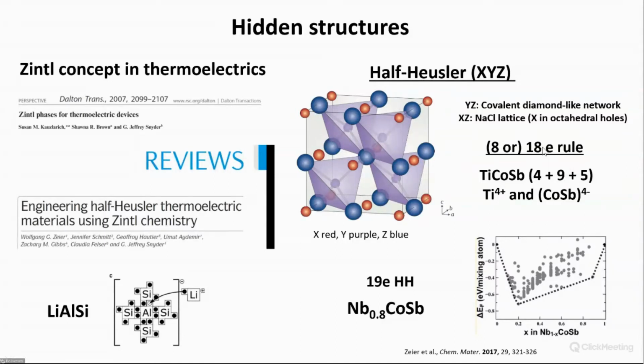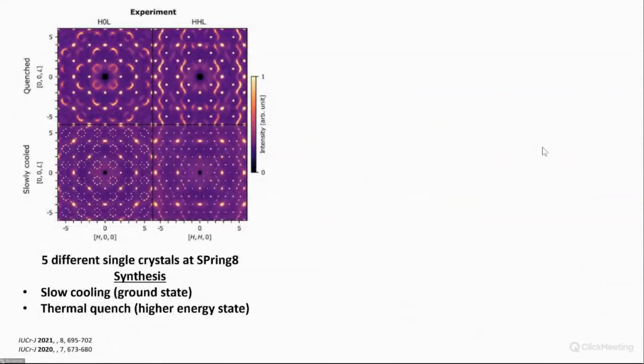This was the thinking for a couple of years, but we then started synthesizing different kinds of these half-Heuslers with niobium, the 19-electron half-Heuslers. We used different methods. One where we slowly cooled it, so we could get a distribution of vacancies that was maybe in the ground state. And then we did various thermal quenches where we could maybe get a higher energy state. Clearly the two crystal structures are different: here's one quenched and here's one slowly cooled. And you see the diffuse scattering here is obviously very, very different.